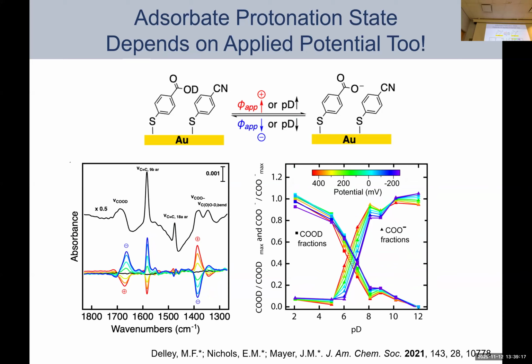Okay, so here you can see that as we apply more positive potentials than our reference point, we see a bleach in the carboxylic acid features and an increase in the carboxylate features. And similarly, if you apply more negative potentials than the reference potential, you see a growth in the protonated species and a bleach in the deprotonated. And so we believe that this is nice evidence showing that there is a potential dependent protonation and deprotonation change.